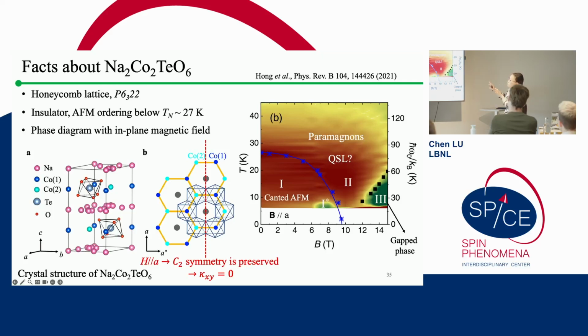However, things are a little bit weird for this sodium cobalt tellurate. If you check the global symmetry, I mean the space group of this material, you will find it holds the C2 rotational symmetry along both the a axis and also along the a star axis, which is another high symmetry axis.